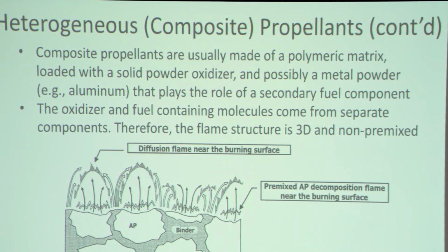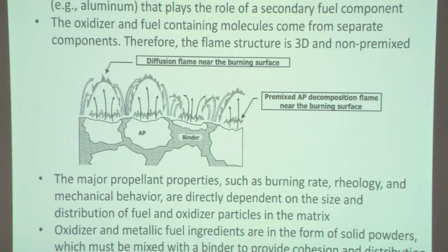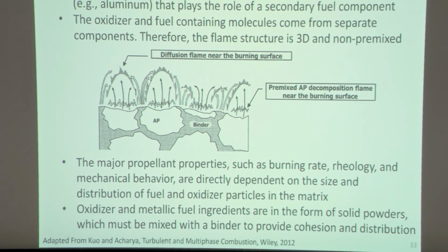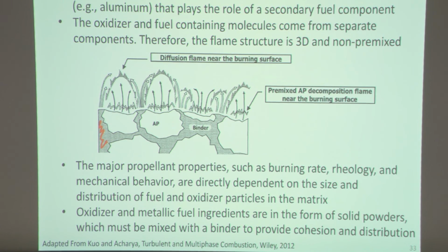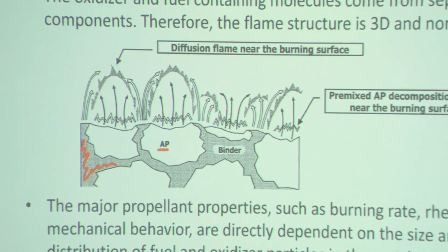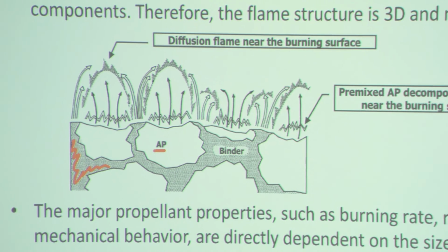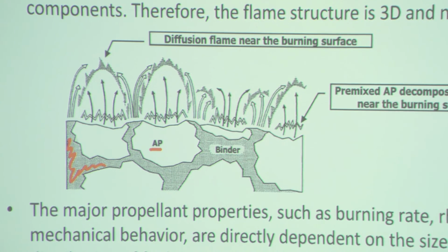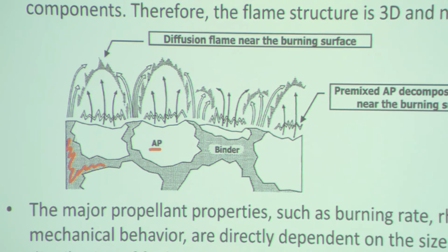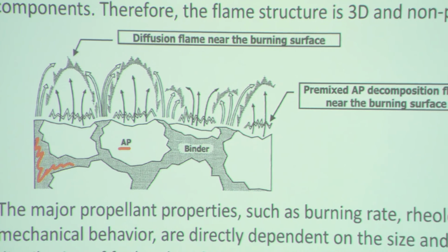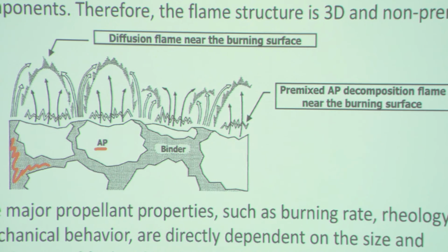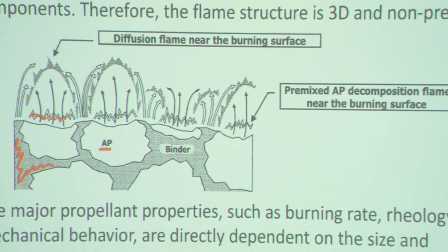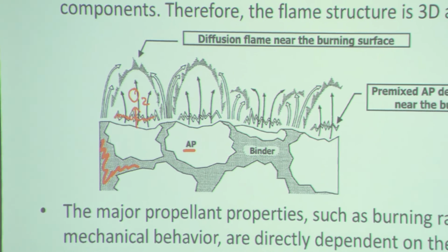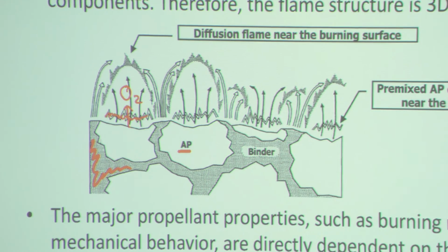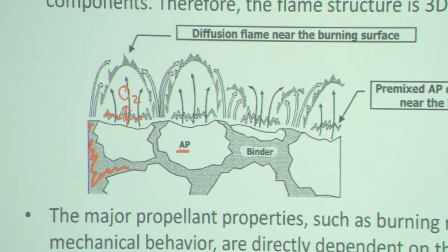So if I go back and look at that structure I showed you on the previous page, and I draw it here, and I say, well, how might the flame structure look immediately above the surface? What I might find is something like this. This out here is the fuel binder, and these large white pieces are, say, the oxidizer crystals, say ammonium perchlorate. And what happens is the ammonium perchlorate is often considered a monopropellant. It can decompose exothermically, like a premixed flame, because it has its own oxygen and a little bit of fuel components. So what will happen is right above the surface, I'll get a little premixed flame. And out of that premixed flame, I'll generate molecular oxygen, about 23%, as I said. Now that molecular oxygen comes out, and this fuel over here that's holding the crystals together, because of the heat, starts to pyrolyze.